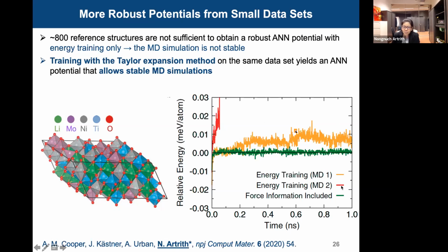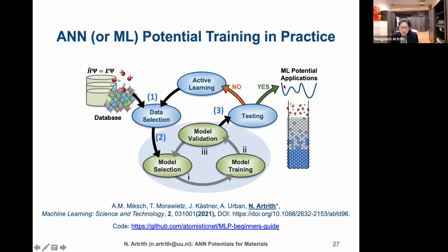And then in the second MD simulation, also using just 800 structures and 800 energies, suddenly the MD simulation just explodes. So this is the demonstration that our new approach to include force information with Taylor expansion improves the MD simulation and makes it more stable. But note that this is just a benchmark. You cannot use these 800 atomic structures in a real application. In a real application, you need to add even more structures and really find what can be used in your own application.